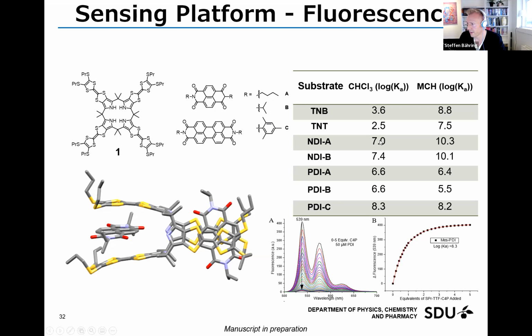But you can see that their binding constants are quite a lot higher than TNB and TNT in chloroform. So if we were to make this indicator displacement assay in chloroform, there wouldn't really be any displacement because it binds the NDIs and the PDIs so much stronger. But if we switch solvent to methylcyclohexane, we can increase the complexation with TNB and TNT dramatically to 10 to the 8th. For the NDIs, where the distance between the carbonyl groups is not as big, they can still perform hydrogen bonding interactions. But for the PDIs, you can see that their binding constants are not increased as well.